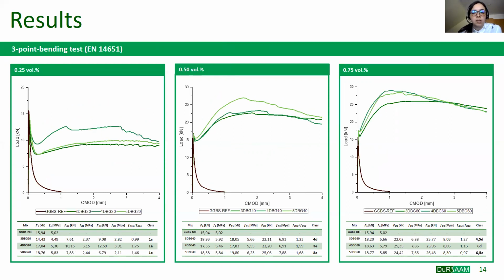In this slide, instead, we can see the load CMOD diagram for every fiber percentage. And as we can see on the left, with the lowest fiber content, so 0.25% volume fraction, the best behavior is obtained with the Dramix 4D fibers, while 3D and 5D perform very similarly, even if they have different performances and properties, especially the tensile strength of Dramix 5D is almost double that of the 3D. This behavior could be due to the compressive strength of the matrix, which is not high enough to allow the 5D fibers to perform